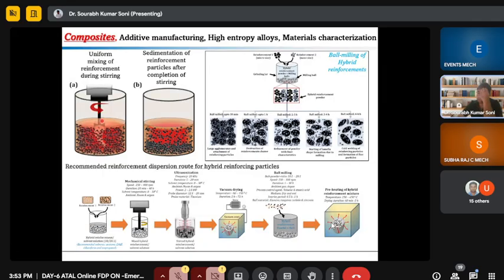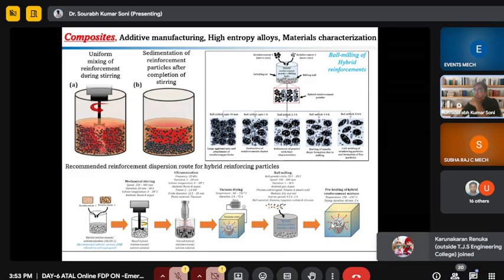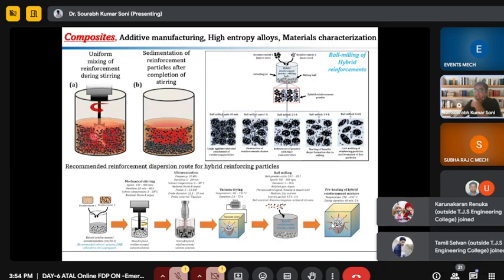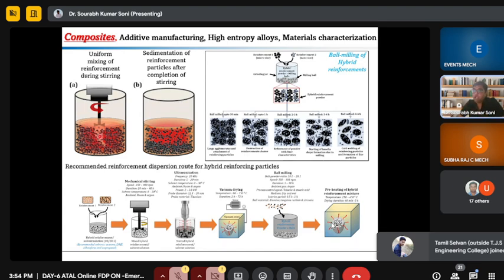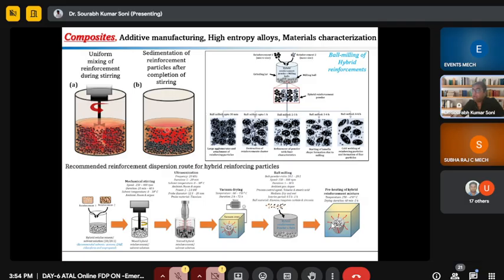In this slide, I want to highlight the most critical part. In stir casting, what is going on? This is the molten metal. Assume this is molten metal, and these black and white parts are the matrix material and reinforcement material. So while stirring, what is going on? It will mix properly. But just after the removal of mechanical stirring, it will again sediment.